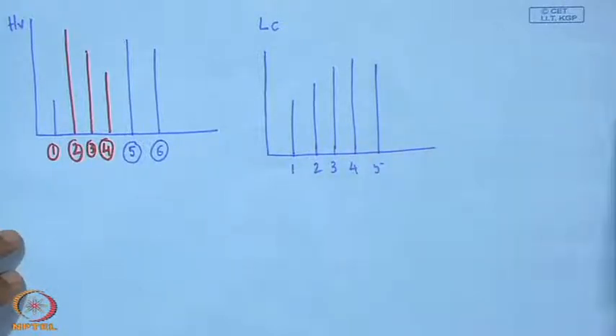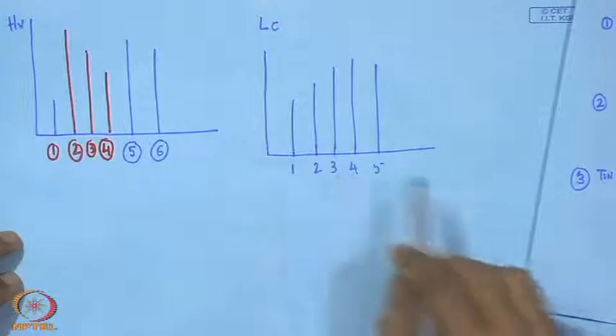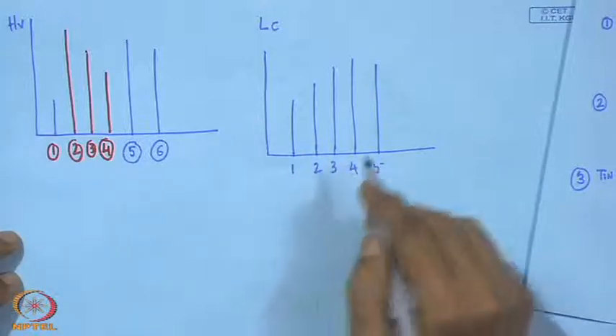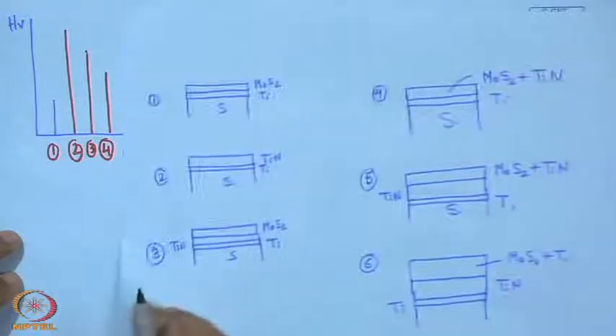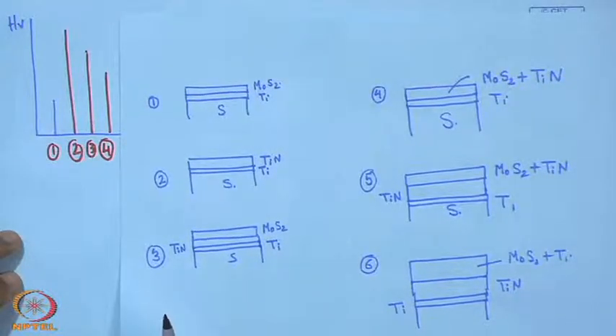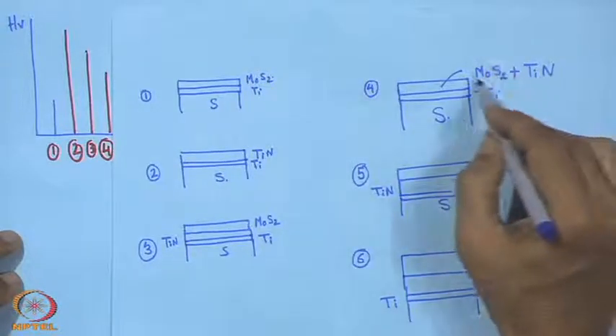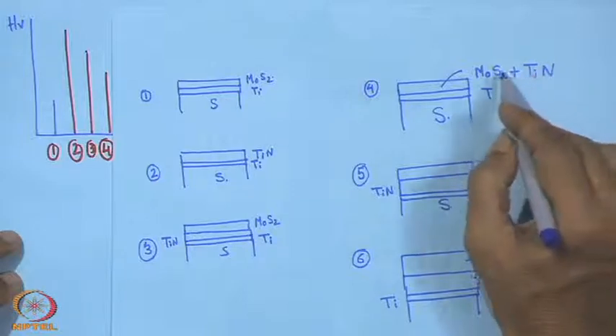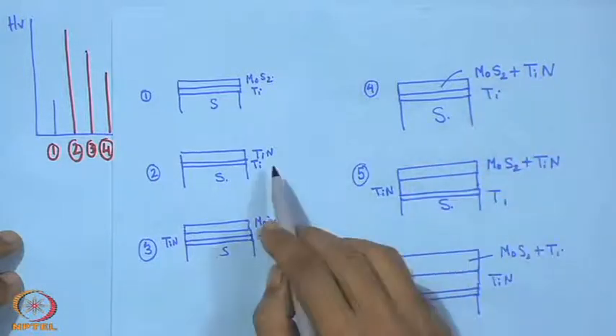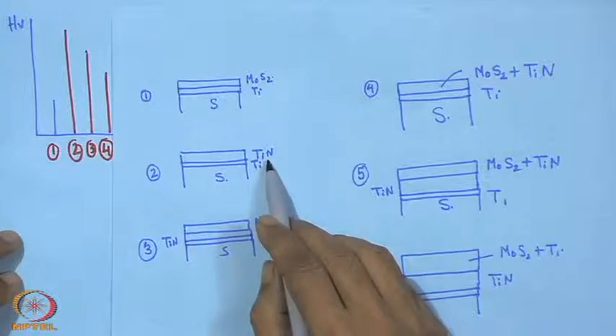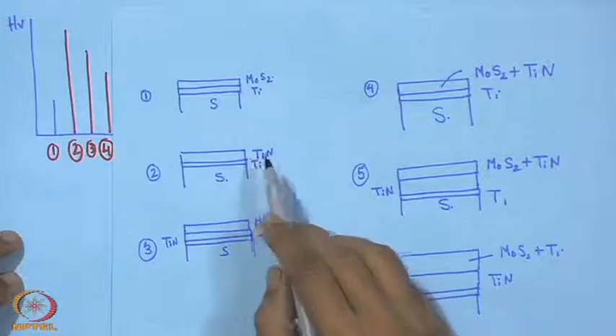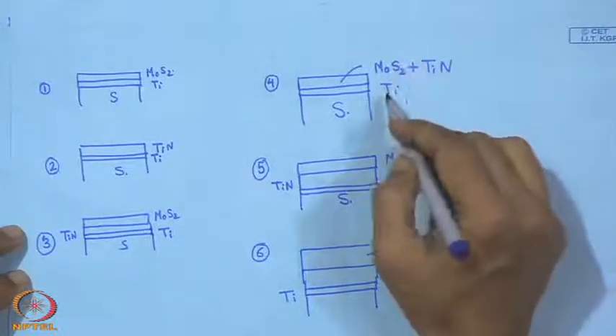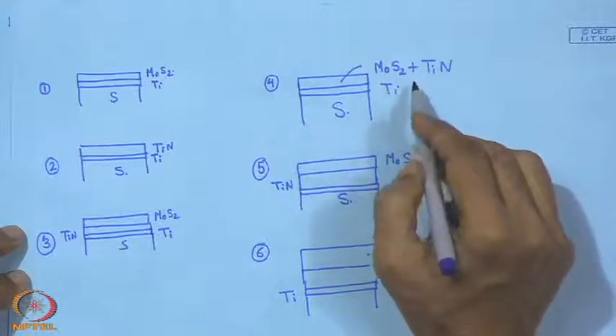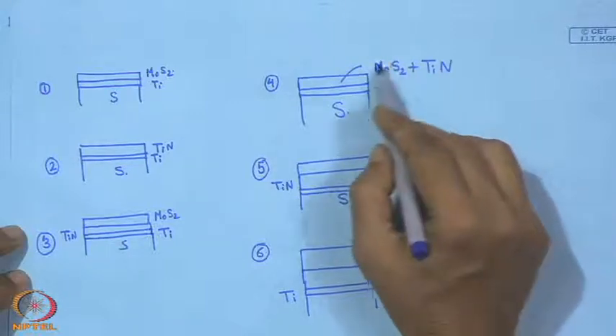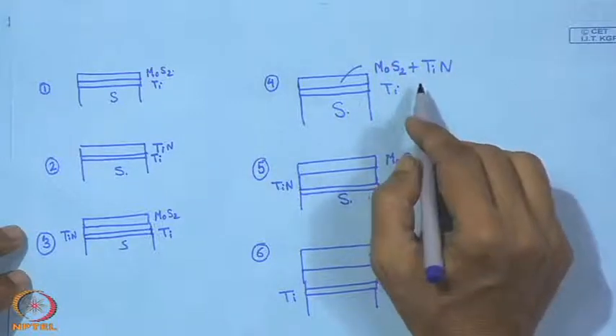Now comes a very important thing. So, for 1, 2, 3, 4 and 5, what we see here is that the adhesion of this one is not so good. Now, in this case what happens with this combination is actually the resistance to fracture and resistance to cracking of TiN, which is coarse grain here and which becomes a little bit micro grain. So, resistance to cracking and resistance to fracture becomes more, and because of this grain refinement, that is why we expect a better adhesion in this case.